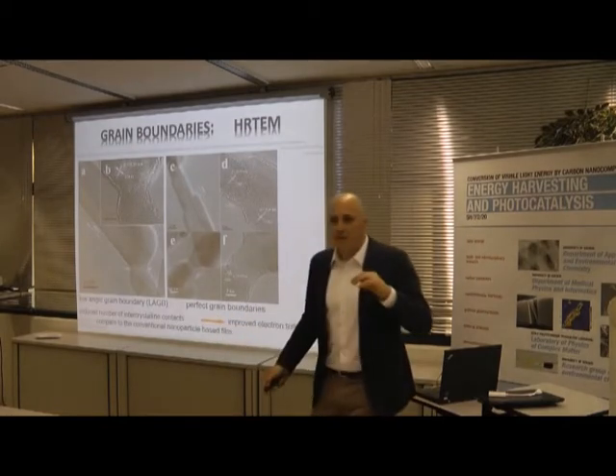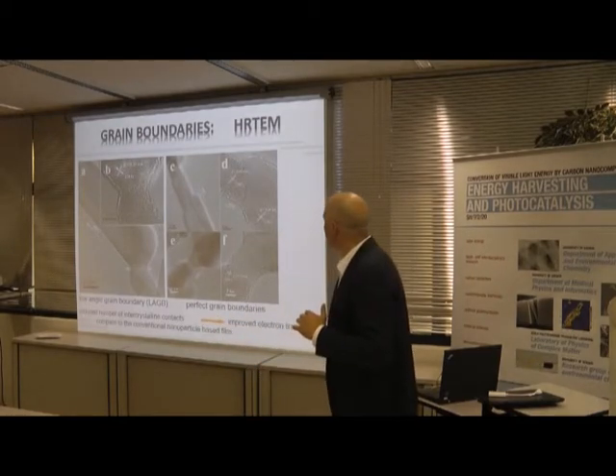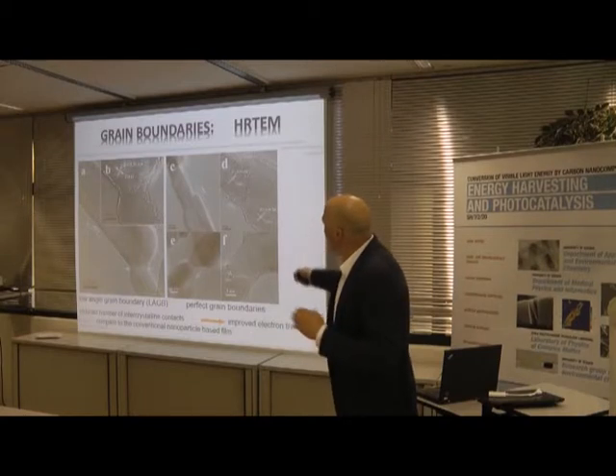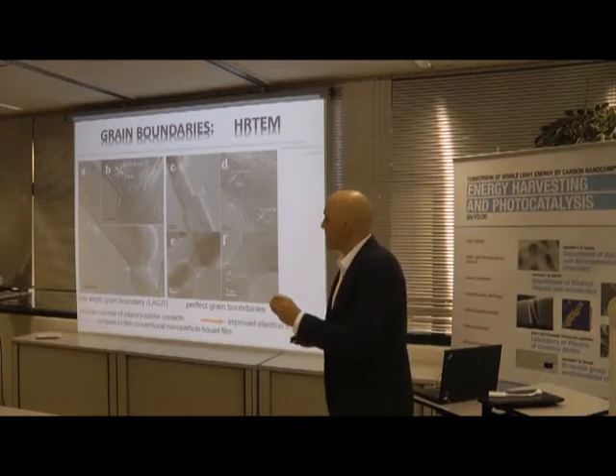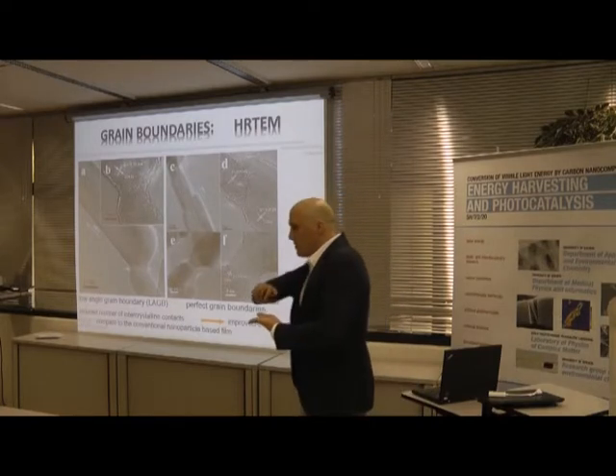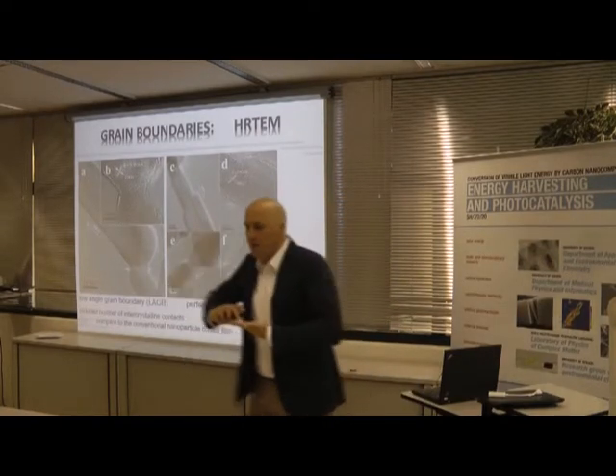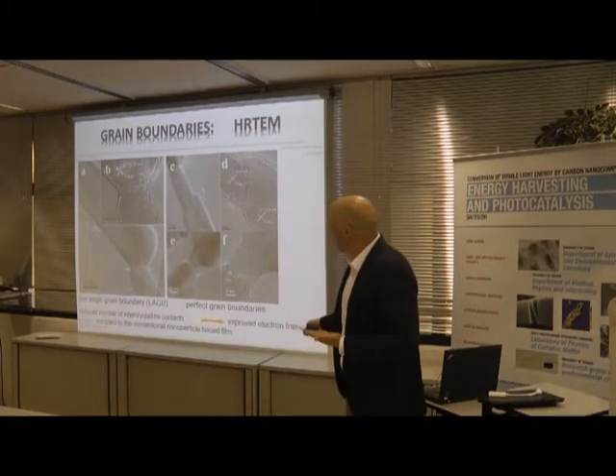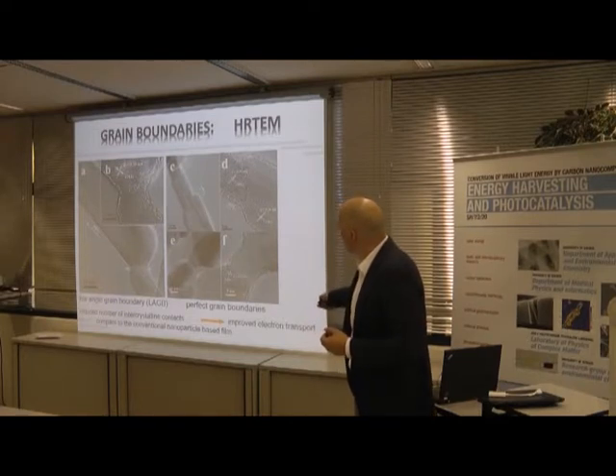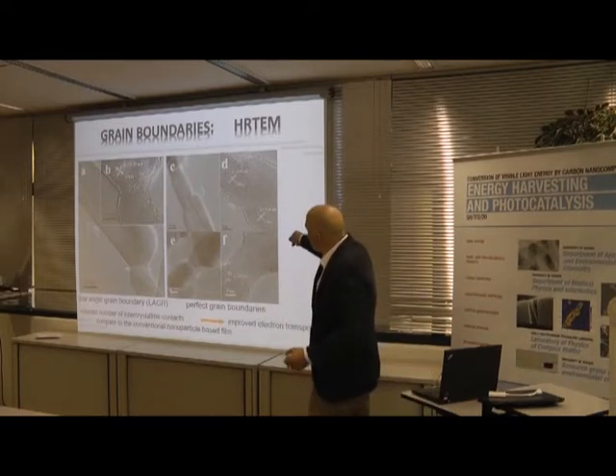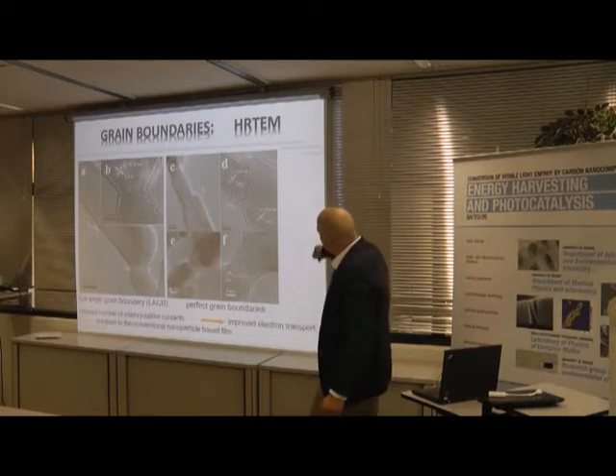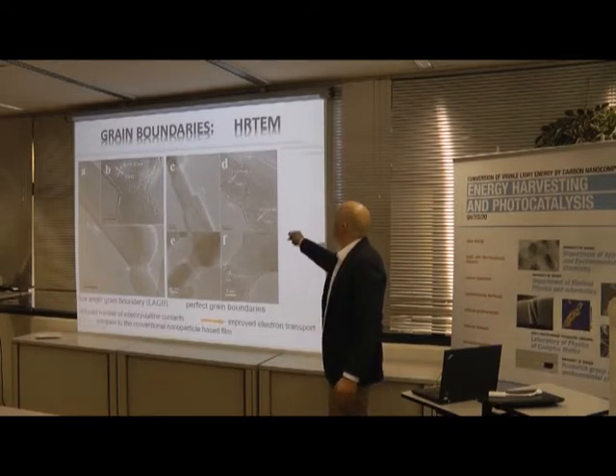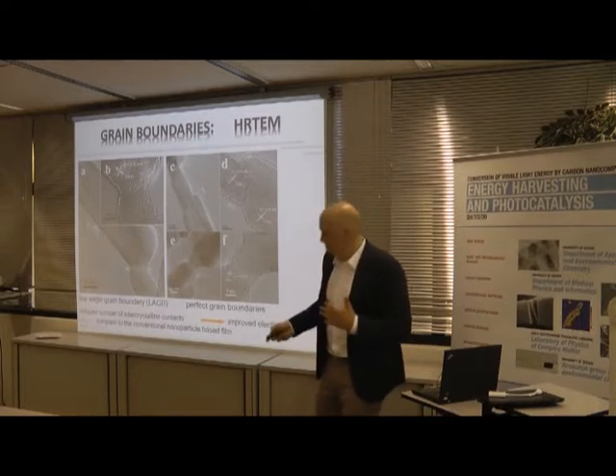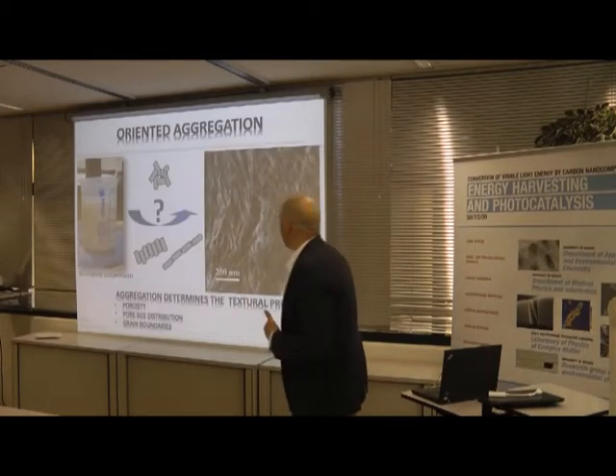What we found was the key to the high efficiency: these nanowires are themselves like single crystals. But when you create your film, you aggregate them, and it turned out that the grain boundaries between the wires are either low angle grain boundaries or perfect grain boundaries. So this is the high resolution TEM image of one wire and the second one here as well. Probably here you see the lattice fringes. They are completely parallel. Here's the grain boundary, but it has exactly the same orientation. So we think that this was the key for the success.